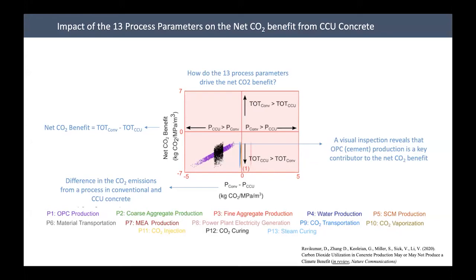So on the x-axis over here, we have plotted the difference between CO2 emissions from a specific process in conventional concrete and the same specific process in CCU concrete. And on the y-axis, we plot the net CO2 benefit, that is the total CO2 emissions from conventional concrete minus the total CO2 emissions from CCU concrete. So the visual inspection will be the first step of analysis. We did this for all the 13 process parameters that I just described in the previous slide.